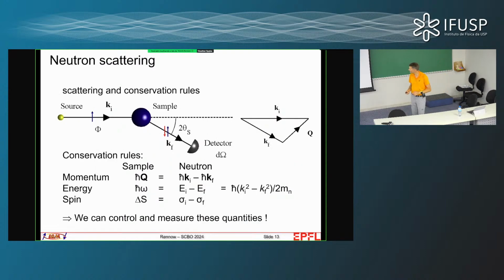But there's one technique that is particularly powerful and which really is one of the reasons why this experiment-theory interplay works so well in magnetism, and that's neutron scattering. Neutron scattering is fairly simple. You take a neutron, you shoot it into a sample, with a well-defined incoming wave vector. Now the neutron is a massive particle, so if it has a wave vector, it also has an incoming energy, and then it comes out, and you can measure in which direction, so how many neutrons are scattered into a particular final wave vector and final energy, and whether or not the spin of the neutron was flipped.